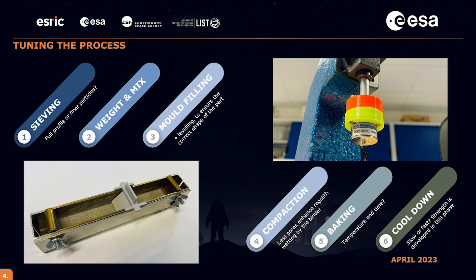Baking, of course, we need to melt the thermoplastic, but we didn't know whether it was better to use high temperature, low temperature, or whether it was necessary to keep them in the oven for a long or a short time. And cool down is the phase in which the strength is developed because the polymer becomes solid enough, no more a fluid.